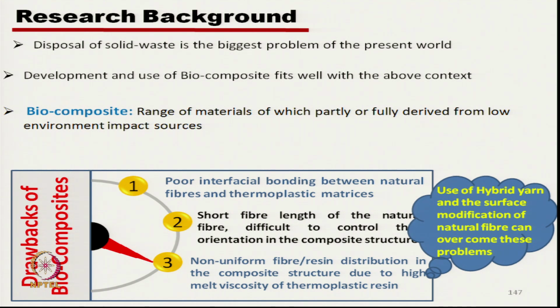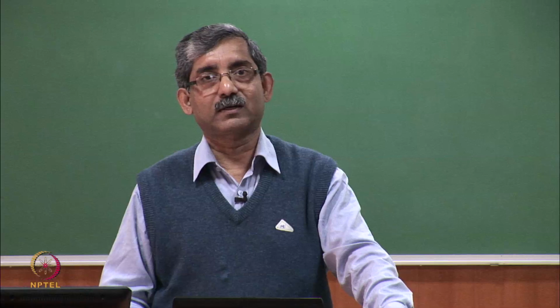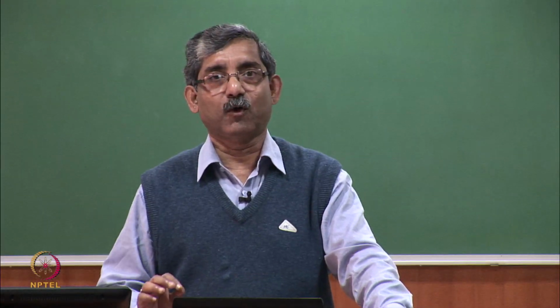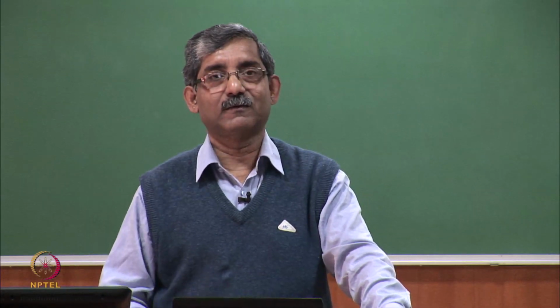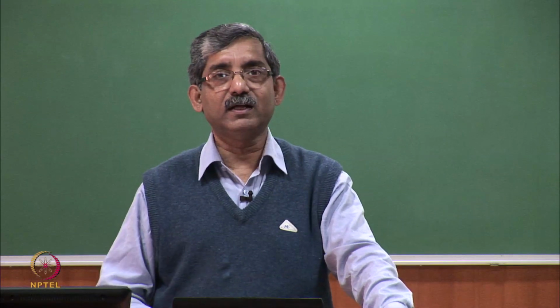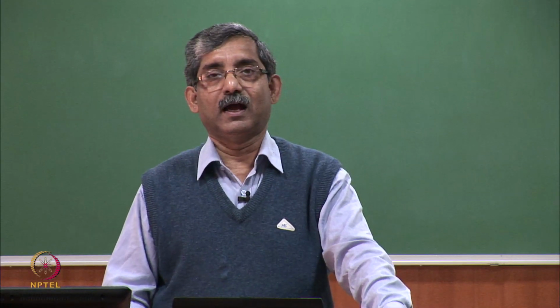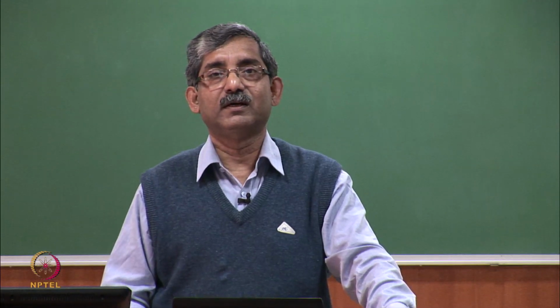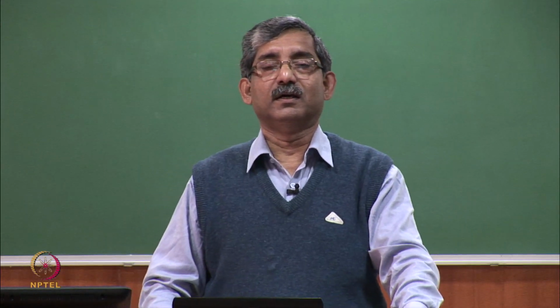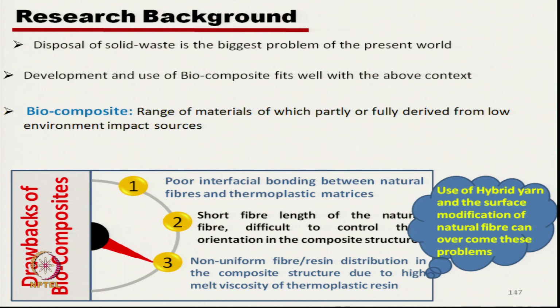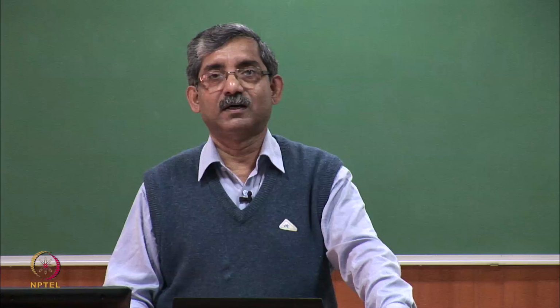So, the approach is that we produce hybrid yarn. Hybrid yarn means, as we have already discussed, where the matrix fiber and reinforcing fibers are mixed evenly together, so that the flow length of the polymer is very short. They are already inside the structure, and the first problem, poor interface between the natural fiber and thermoplastic composite, is overcome using surface modification. Okay. So, these problems we can overcome.